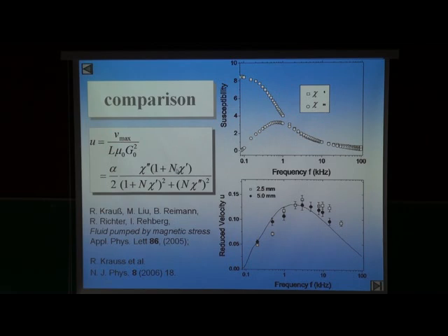So you have here a product. This is very important because due to that product, you have to have both a high real and imaginary part. Here you have again a square of the real and imaginary parts, and n is some kind of demagnetization factor. And alpha is also some kind of factor you have to calculate.